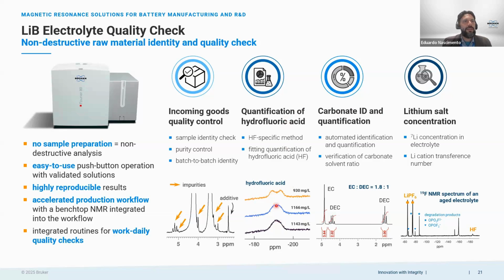You can see here in this example the HF peak. So that's why we say that with our method you are quite selective, because you are analyzing the HF peak. But we have also included the automatic identification and quantification of carbonates and the lithium salt concentration.